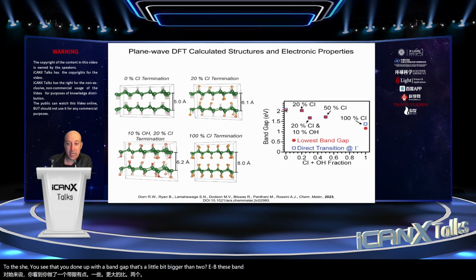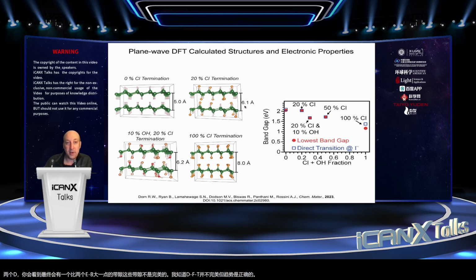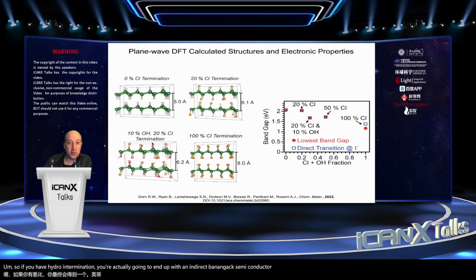These band gaps aren't perfect. It's well known that DFT doesn't get these perfect, but the trends are correct. So if you have hydrogen termination, you're actually going to end up with an indirect band gap semiconductor. However, if we start to introduce chlorine or hydroxyl termination, you see you're able to drop the band gap and you're able to get a direct band gap material.